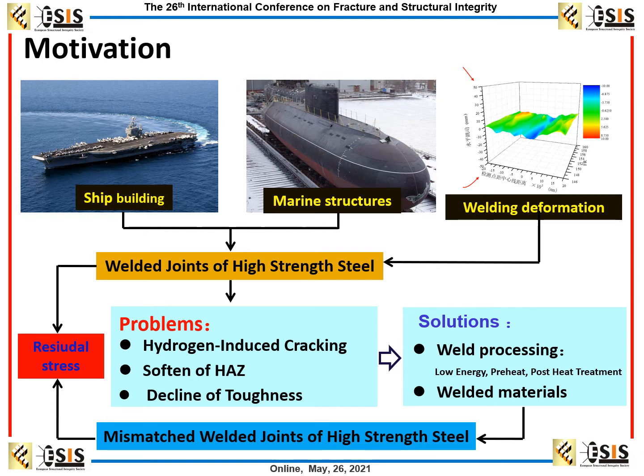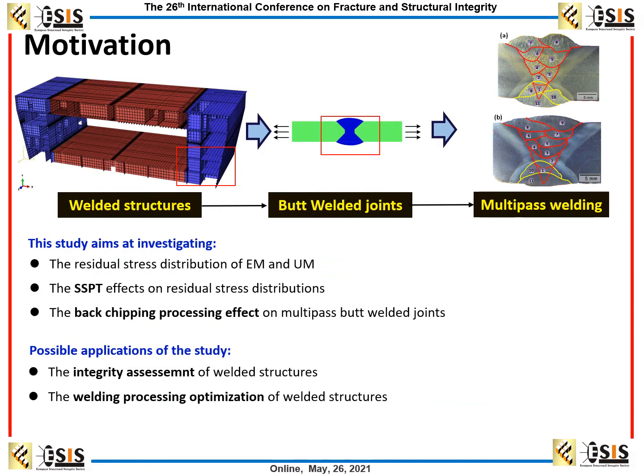So for these materials, how about the residual stress? It is very important to assess the distribution, which affects the fatigue properties of the welded joint. So this study aims to investigate the residual stress distribution of even matched material and undermatched material, and the SSPT effect on the residual stress distribution. The third is the back chipping processing effect on the multi-pass butt welded joint. So I think the possible application of this study is that it can be used in the integrity assessment of the welded structures,